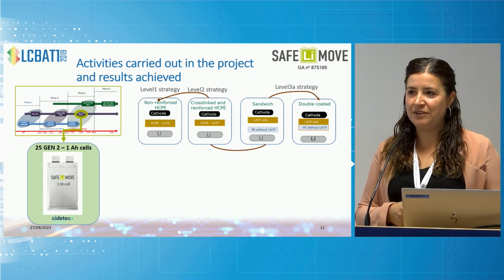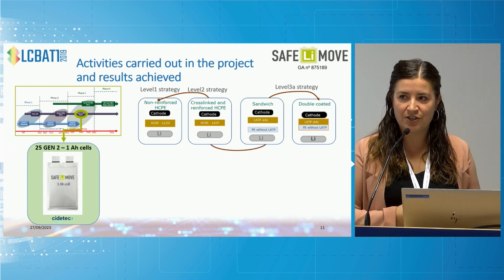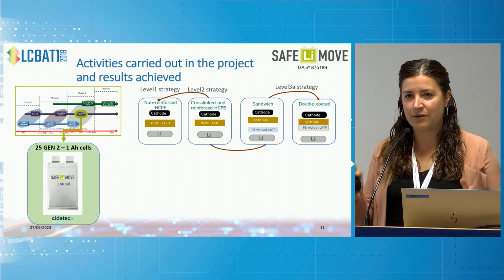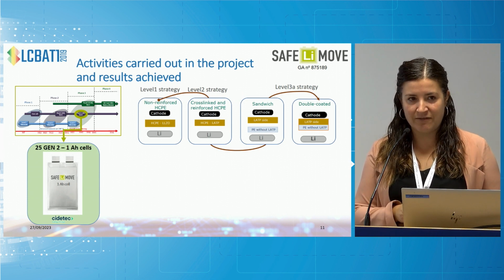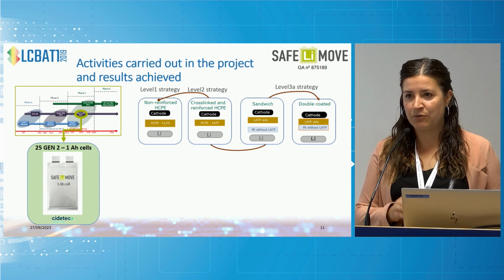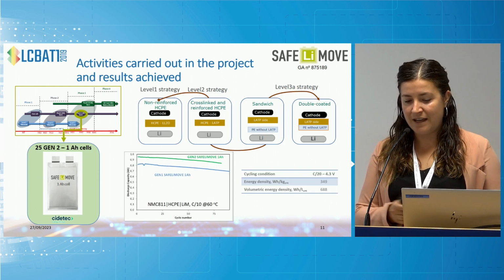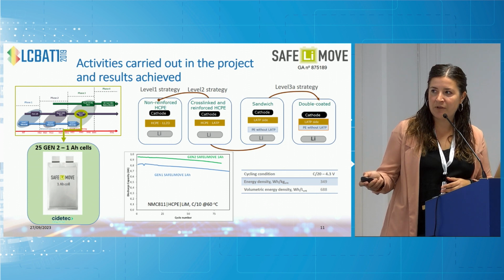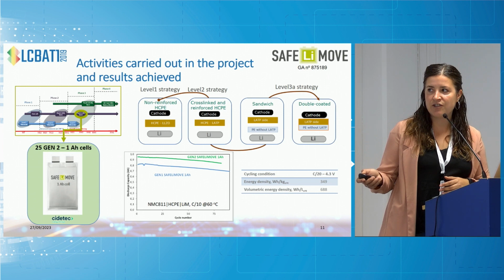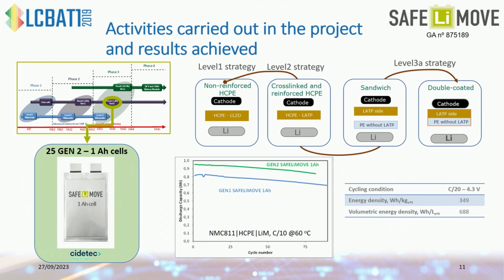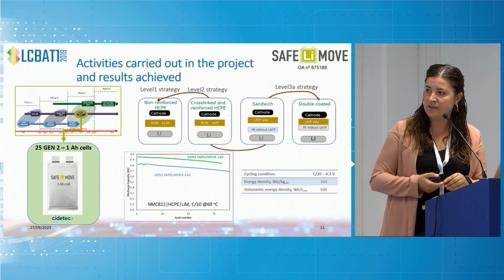And now we are at the point where CIDETEC has assembled the second generation of 1 ampere-hour cells with all this new chemistry. The cells have been shared already with the partners, but we have some preliminary results. Here I'm comparing the performance of the first generation SAFELIMOVE 1 ampere-hour cells with the second generation. We can see that we have increased the capacity by around 15–20%. We ascribe this mainly to the tuning or engineering of the different components, which allows for more stable interfaces.